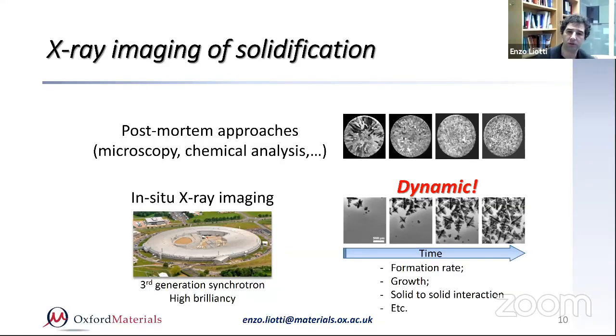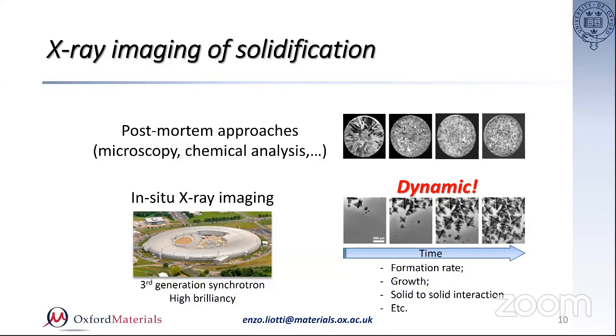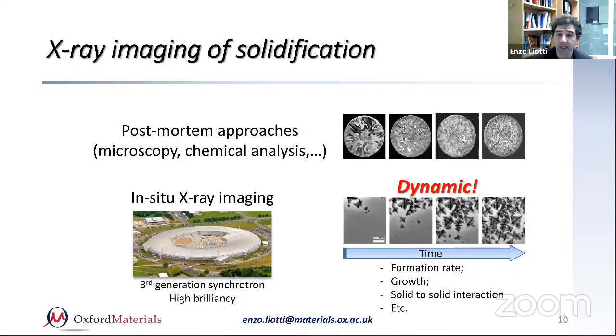Therefore, using in situ imaging with modern third generation synchrotrons, which are quite widespread nowadays on pretty much all continents, allows you to see the dynamics. And by seeing the dynamics of solidification, you can learn about the nucleation and growth of the various phases, the solid to solid interaction, and so on. It gives you really a lot of information.